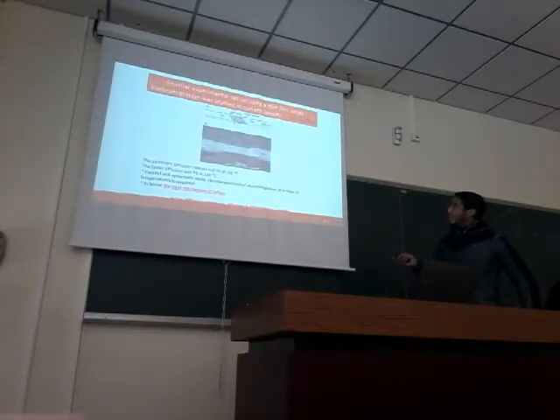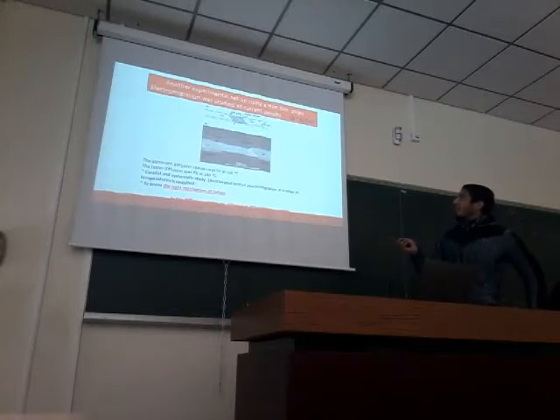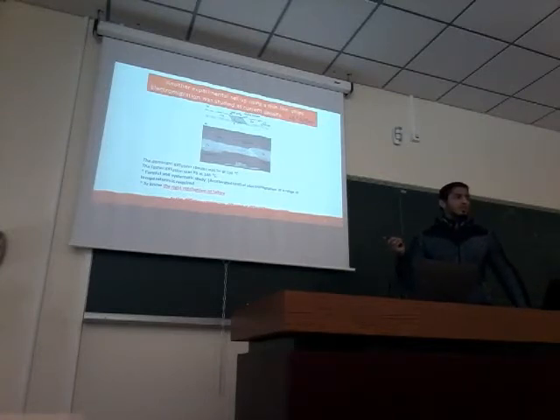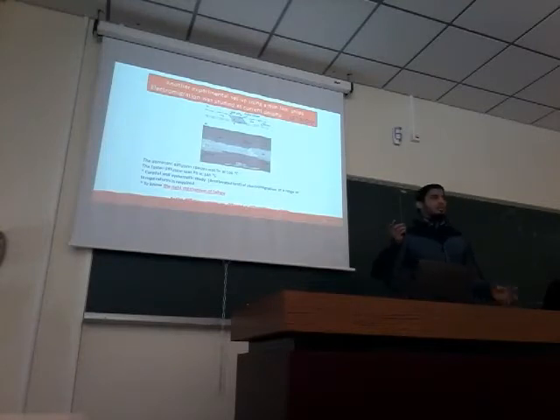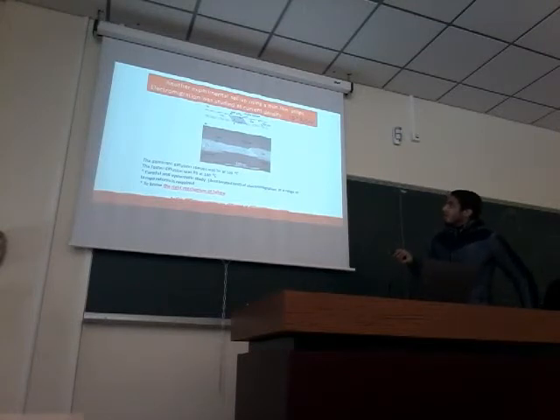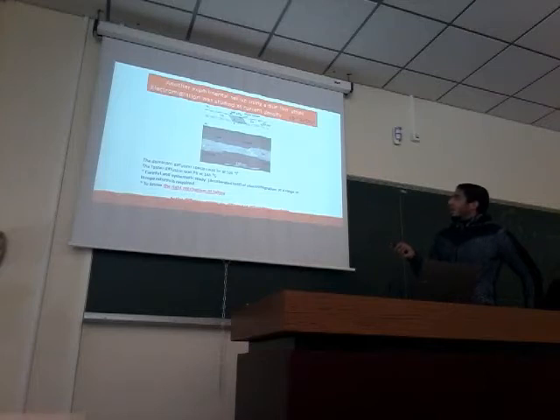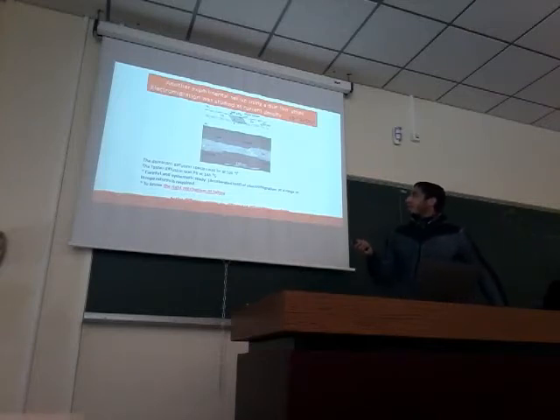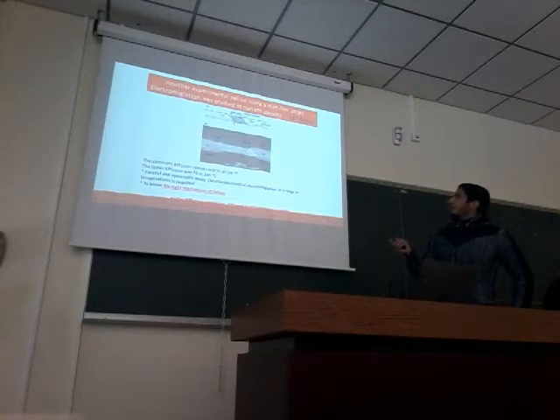Another experiment set up using a thin film strip, electromigration was studied at current density 10 to the power 5 ampere per centimeter squared. This experiment took place at room temperature for 5 days. And we can conclude from this experiment that we have the same observation, the formation of void here at the cathode, formation of